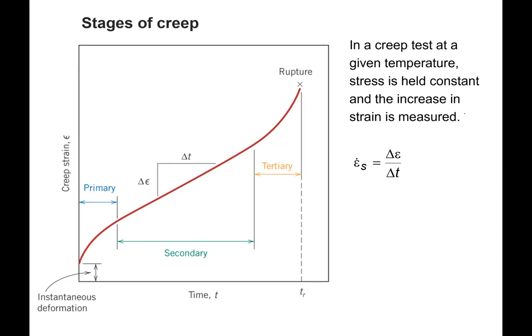So this is a plot here of the strain, creep strain, versus time. And the difference between the creep effect versus a tension test is, remember, tension test, we're increasing the stress as a function of time, measuring strain. In creep, you're basically applying a single stress value, and then you're just monitoring it over time, and it continues to deform.